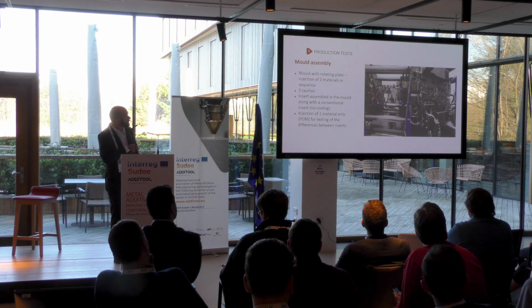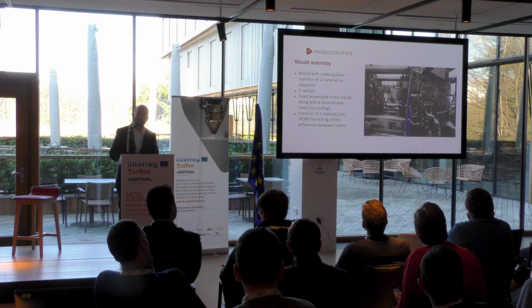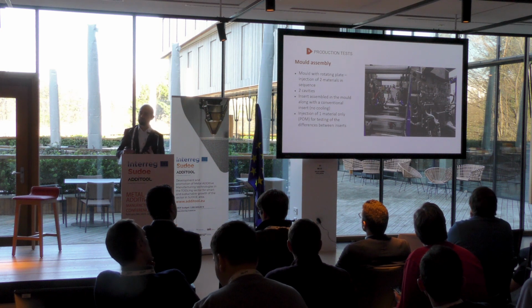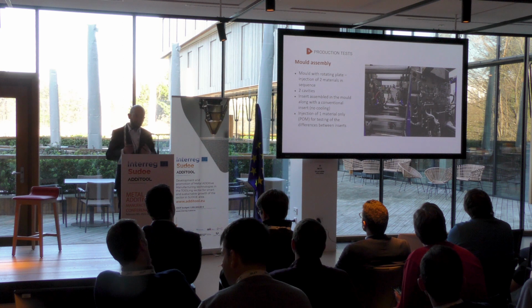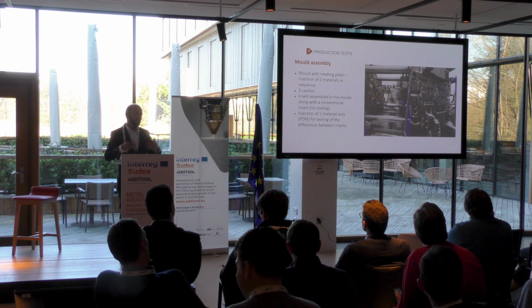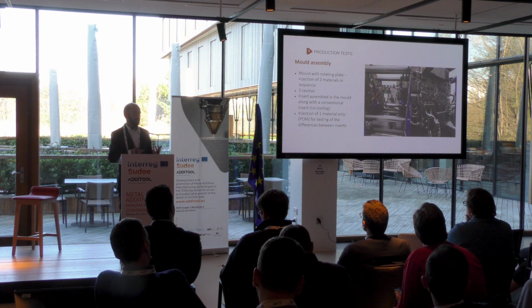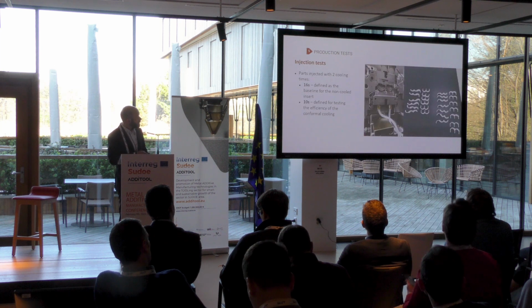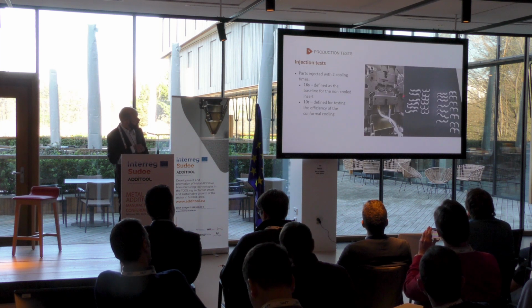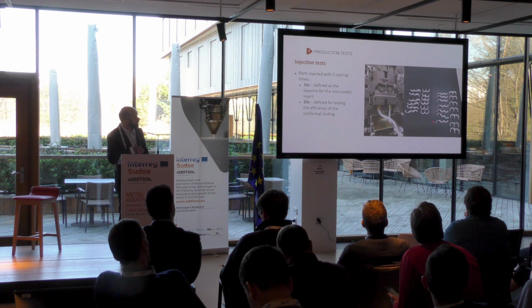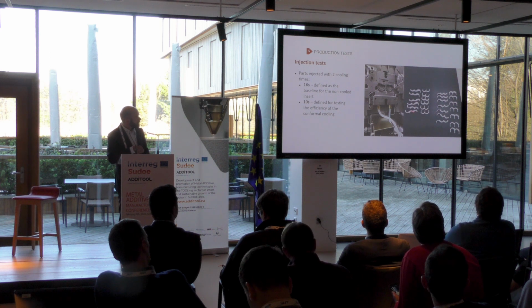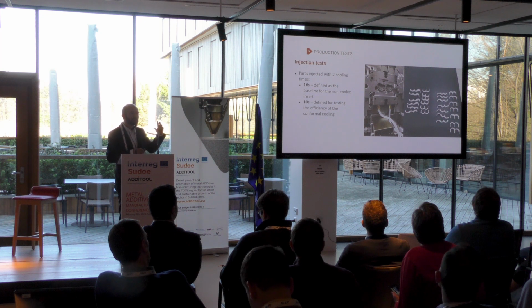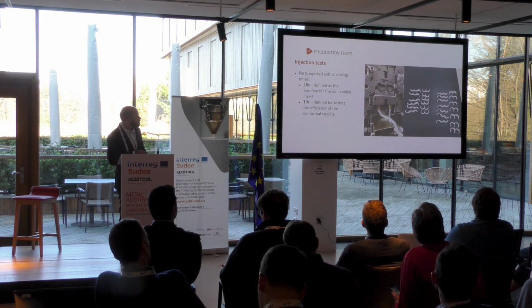The injection was made with the material POM. This was on purpose, to try a difficult material, because POM has a lot of contraction. So the idea was to ascertain the level of contraction of the parts after the injection molding. So we injected these parts. These ones are from the conformal cooling channels, and these ones are from the conventional one. There are slight differences and some defects, but this is not about the cooling itself, it's just about differences in the finishing of both inserts.